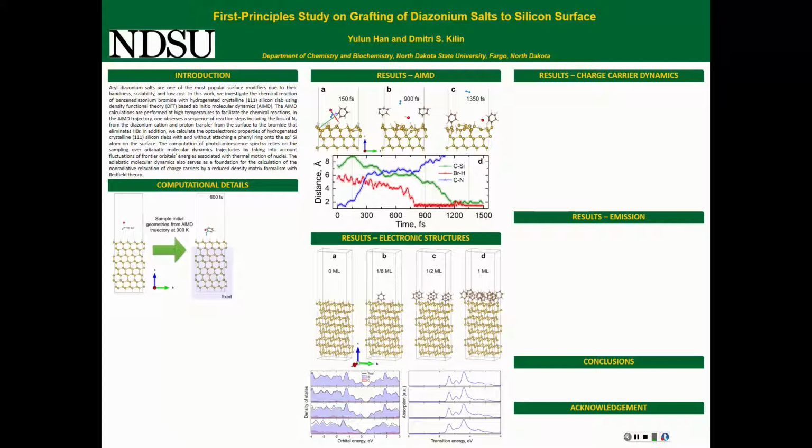So a silicon atom on the surface forms a chemical bond with carbon. See, the carbon to silicon bond stabilizes at 2 angstrom. As soon as the reaction comes to this metastable state, one needs to cool down and perform electronic structure exploration at low temperatures. So you may have some objections about electronic structure at elevated temperatures.